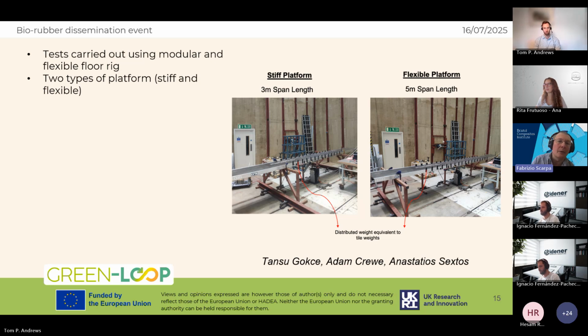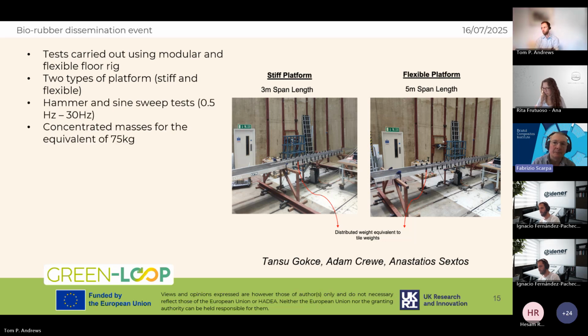Hassam has shown results related to different types of coated and compounded rubber sheets. I would say that really the dimensions are really lab scale, small scale. The results that I will show here are related to the large scale compounded rubber panels for construction applications. And we are talking about rubber panels that are made with lignin reinforcement, up to 20% of weight fraction of lignin reinforcement.